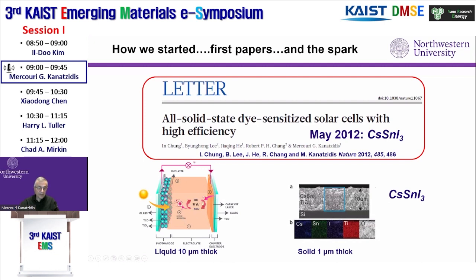So this is the Gratzel device in the lower left. It's very thick and it has acetonitrile. And the reason it has that is because it has to transfer the holes across the device. The electrons go on the other end after they're absorbed by the dye. And this process is a redox process. It's a redox chemistry of iodide and triiodide in solution. In other words, we needed a p-type material that could be deposited from solution, and that's what we had with cesium tin iodide, and then demonstrated 10% efficiency in this thing, which took the entire community by surprise.